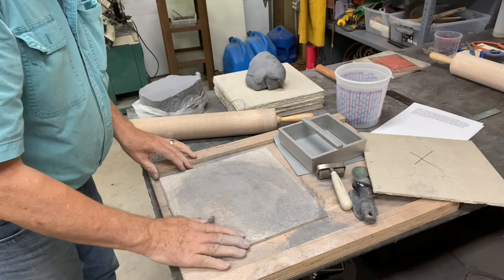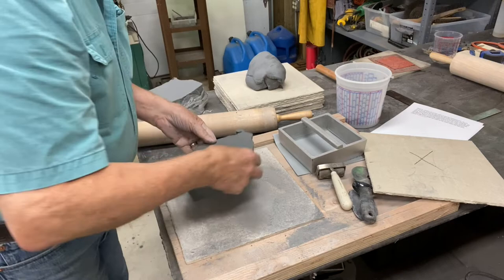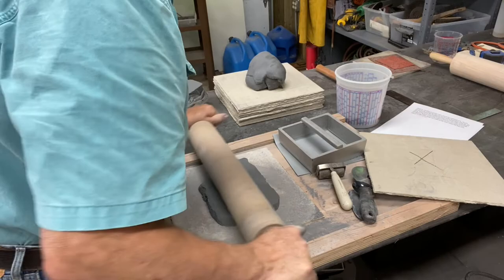For making tiles, I use a sculptural mix containing a coarse grog, as this makes the clay much less prone to warping. Most often I use either Mass White SS earthenware clay or Mass Red terracotta that I buy online from Sheffield Pottery and have been pleased with the results from both.